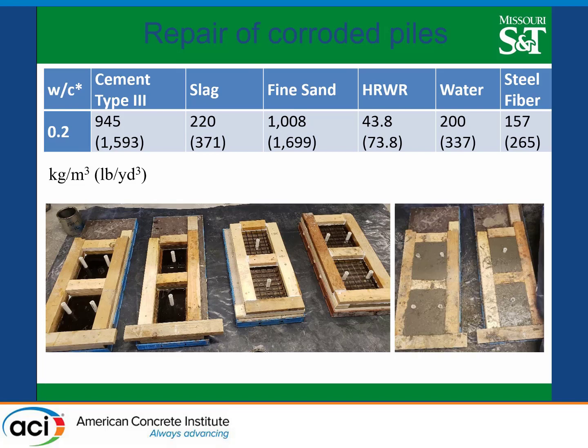And this mix over here gave us 20 ksi after 3 days. Those were cured 24 hours in steam curing at 70 Celsius, and then we put those for another couple of days in a chamber where they are subjected to some moisture. Some of those are just UHPC plates. The others, we installed some of the carbon fiber grids. This is the carbon fiber. Some of those were just a single layer of carbon fiber in the middle of the plates. Others we have layers.